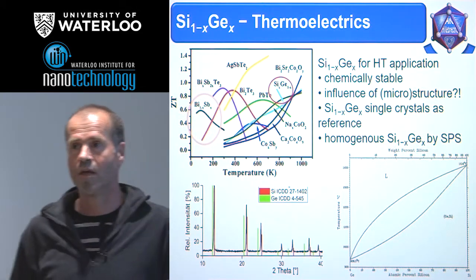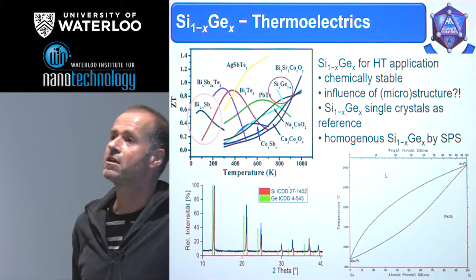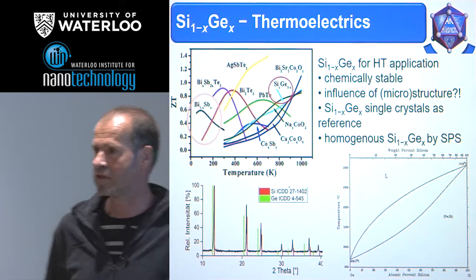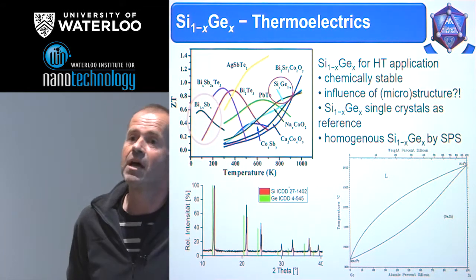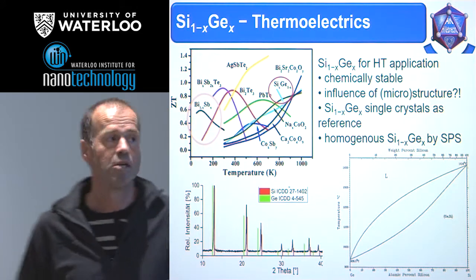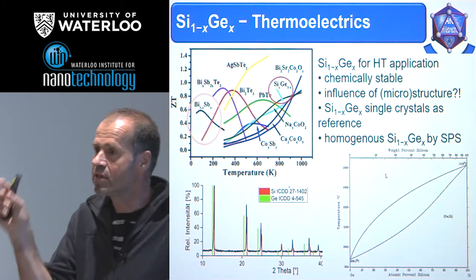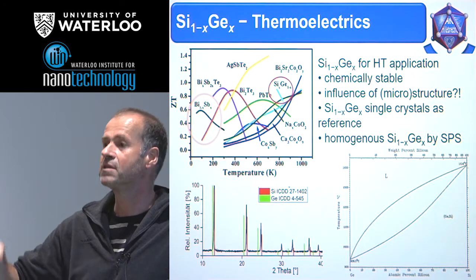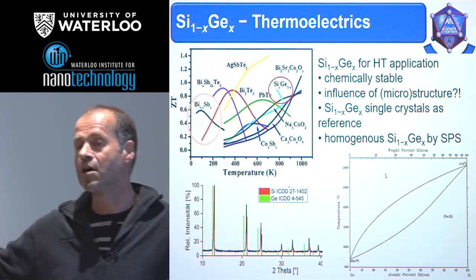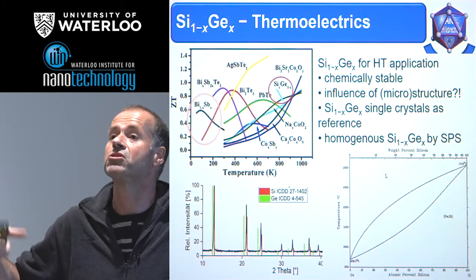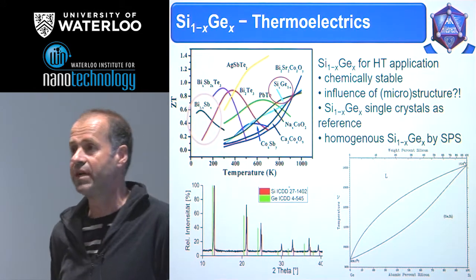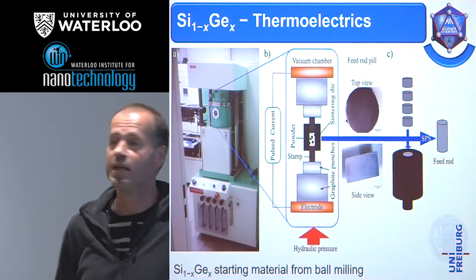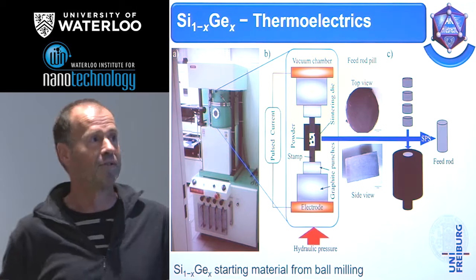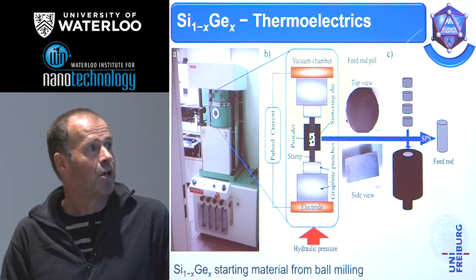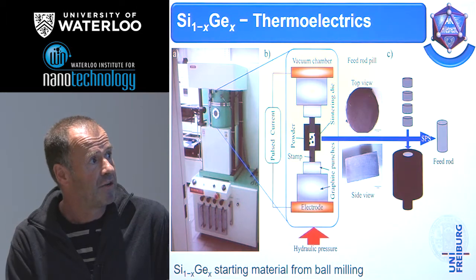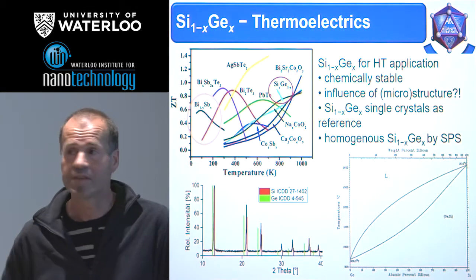And so our idea was, we just grow a single crystal, and a single crystal has no influence of the microstructure because it is a single crystal, and we have a system which is chemically quite stable. So we put a part of this single crystal and can use it as a reference to validate all the ZT machines which measure these values. And this idea was developed together with one of our Fraunhofer institutes, and that's how we tried, no, we did, we realized it. That means we make a material by the SPS synthesis as a pellet.